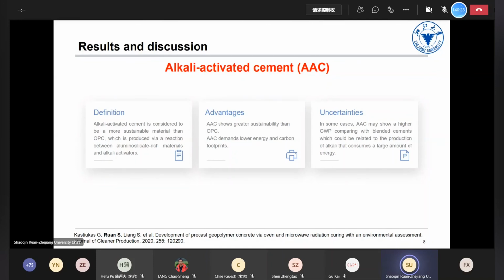However, there are some uncertainties. In some cases, AAC may show a higher global warming potential compared with blended cements, which could be related to the production of alkali that consumes a large amount of energy. As we know from the definition, to prepare alkali-activated cement, you need a large volume of alkaline. The production process of this alkaline may be energy intensive, so it further adds some environmental burdens to the whole process.